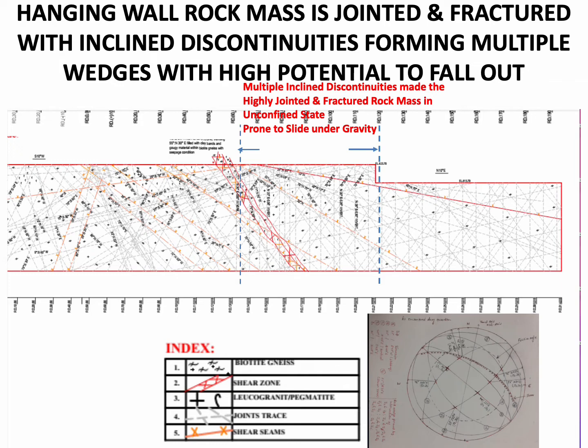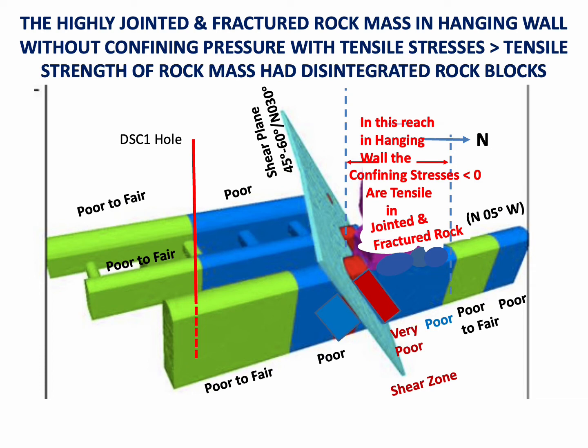In this reach, the confinement has been lost, discontinuities are inclined, there are potential wedges, fracture sets, which are making all these blocks prone to slide under gravity. Same thing shown here, that in this hanging wall, in this reach, the confining stresses have become zero in the jointed and fractured rock mass. With the presence of inclined discontinuities and fracture sets, the potential wedges are prone to slide in this reach where the confinement has become zero, or even there are tensile stresses in the transverse direction, which should be responsible for creating an arch action.